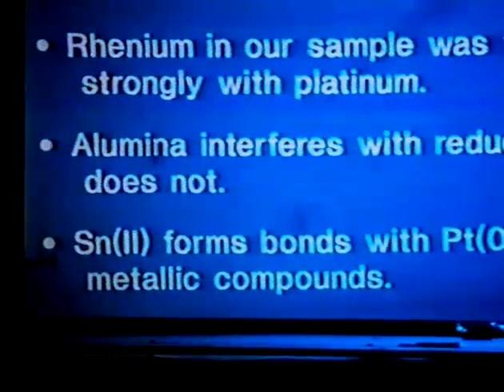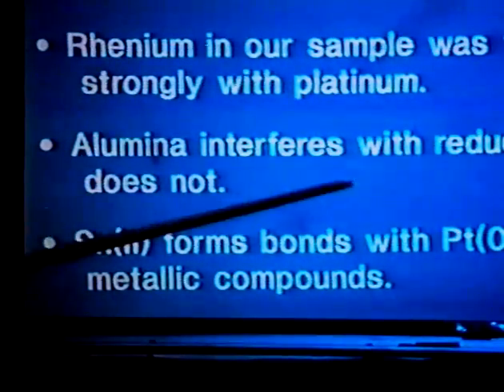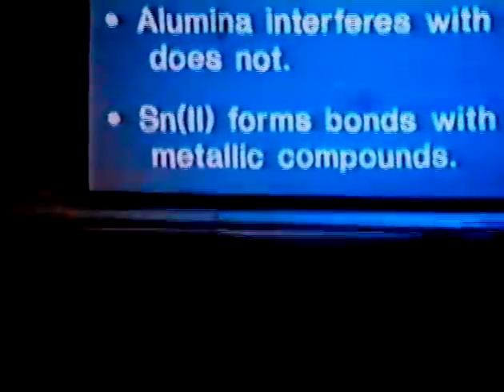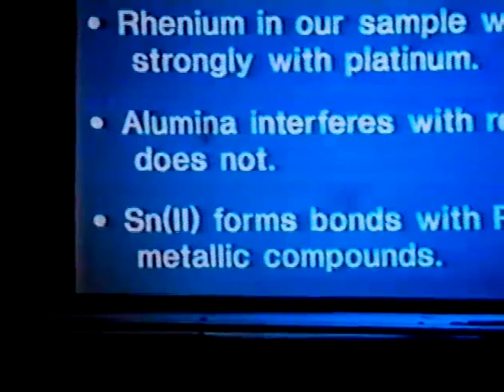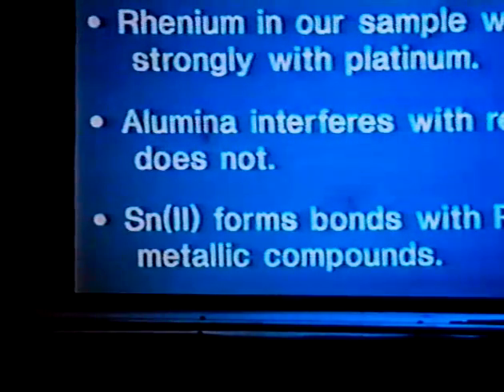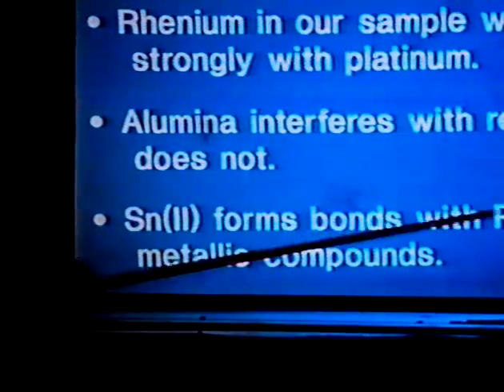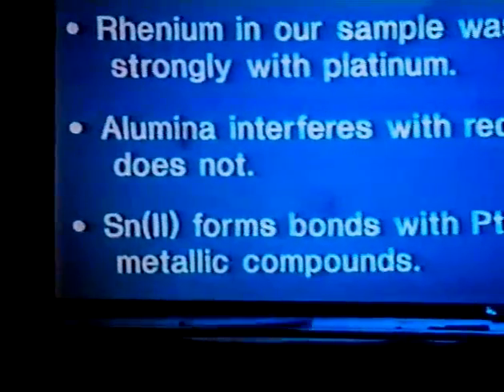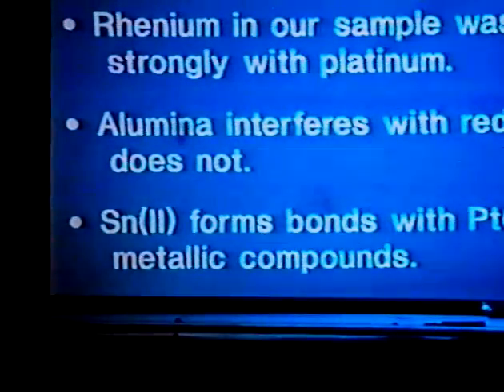There was a lot of platinum-rhenium interaction. That was, I would say, a true bimetallic catalyst, and these were well-mixed clusters. Alumina interferes with the reduction of tin-2, and silica does not. This I would call a true example of a strong metal support interaction, and one that's significant in the area of catalysis, as opposed to another kind which certainly happens, but is hard to demonstrate a use for. And finally, tin-2 forms bonds with platinum-0, whereas tin-0 forms intermetallic compounds.